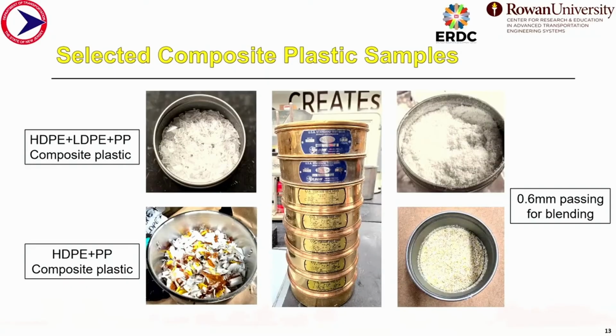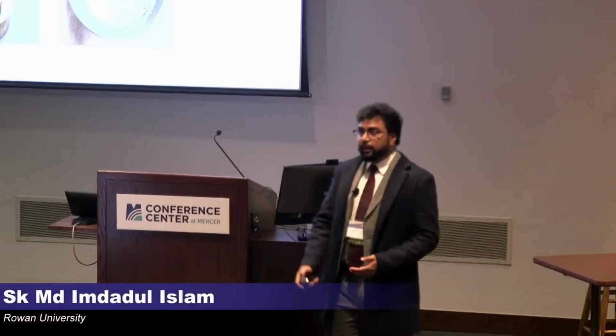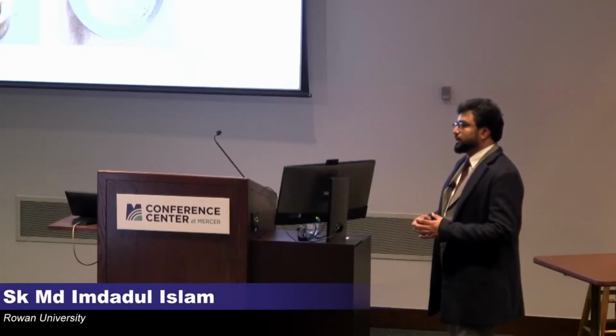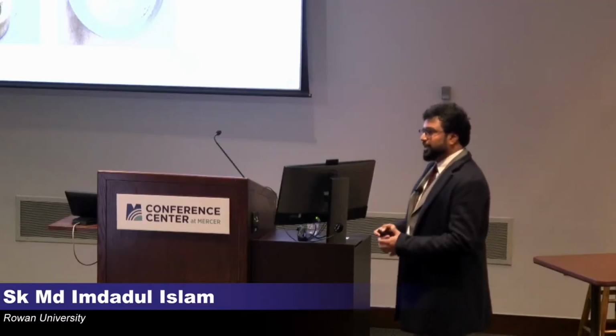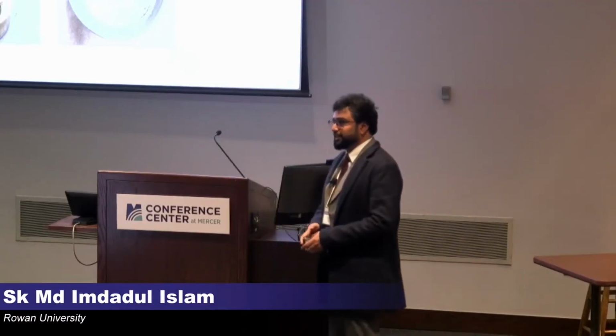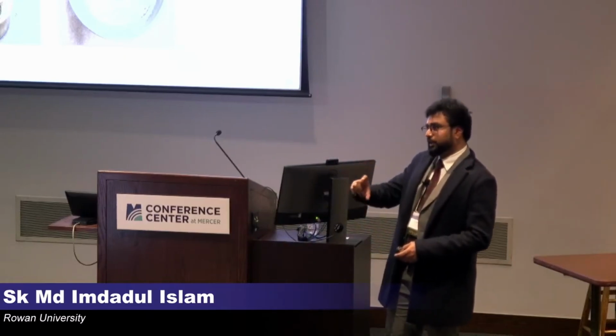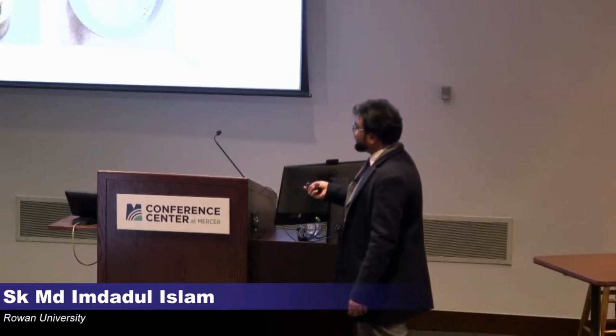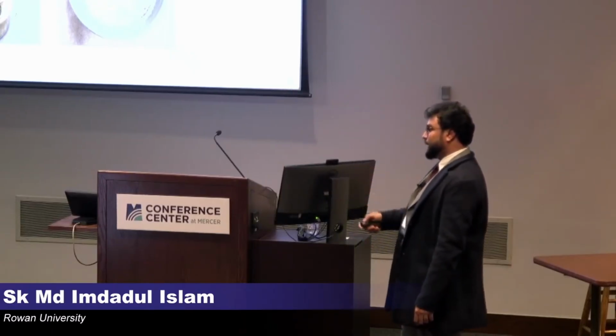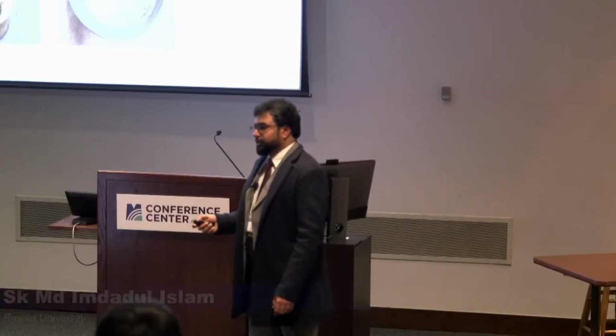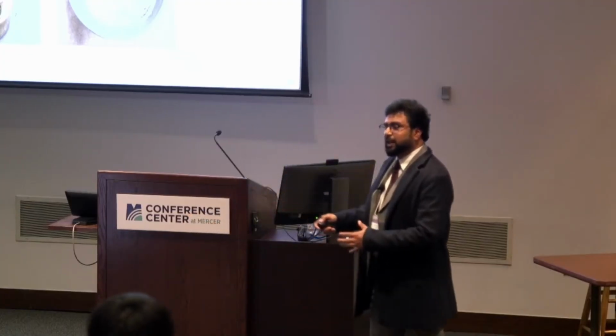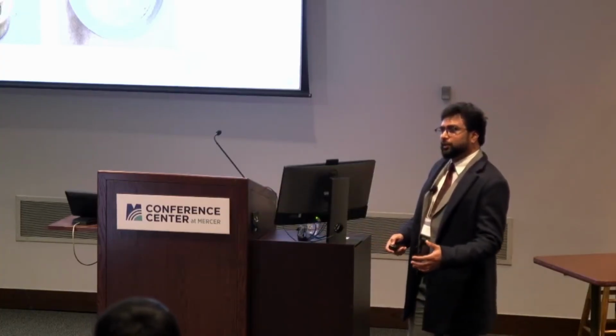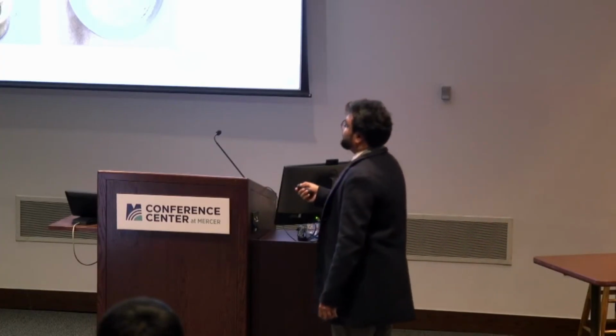With that objective, in our project, we selected two types of plastic. In most of the previous research, researchers use a single source of plastic, like only LDPE or HDPE or polypropylene. However, in the real field, the plastics are not like that. They come as a mix, most of them are mixed-use plastic. If we look at a plastic bottle, we can see the top cover of the bottle, which is HDPE, and the lower part is LDPE. So in real life, most of the time we have composite plastic, and according to the plastic recyclers, it's sometimes very hard to separate these mixed plastics, and that's why they lose their demand for recycling purposes.